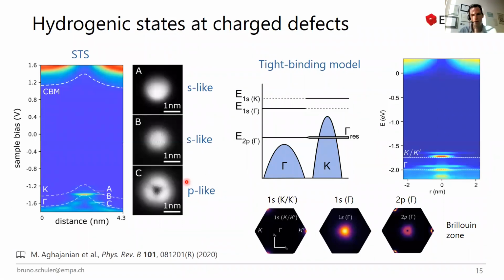Now, something which was quite peculiar to some of these defects is when they are charged. So when they are charged, they do not only show orbitals which are associated to chemical orbitals, but in fact also hydrogenic bound states. And this should be shown here. So this is a negatively charged defect, so this carbon defect. But at that time, we did not even know what it was, but just a negatively charged defect. And how you can see this is at the positive biases. So the conduction band is bending up, so it's repelling the electrons in the conduction band. But on the other hand, this negative charge is an attractive potential for holes in the tungsten disulfide. So it localizes holes. And these states actually even look like prototypical hydrogenic states.